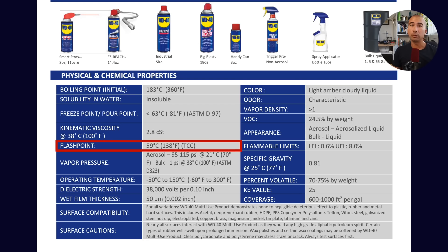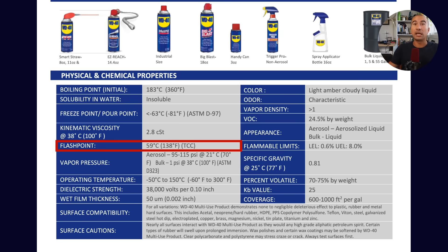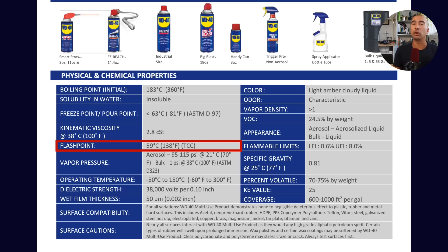Another interesting property is the flashpoint, which is very low. That makes sense because when you have low C number molecules, these are light and tend to be more volatile — more gas-like. As we go to something like C1, which would be methane, methane is obviously a gas and very volatile. Then as you go to propane and butane, they tend to form gases very easily. If you're pretty adjacent to that — C8, C9, C10 — there's going to be a lot of vapors formed. That's another reason why WD-40 doesn't really make a very good lubricant, because after you've sprayed it, so much of the liquid volatilizes off that it doesn't remain in place as a lubricant for very long. The flashpoint tells us a lot about the fact that WD-40 isn't necessarily going to stick around in the long term.